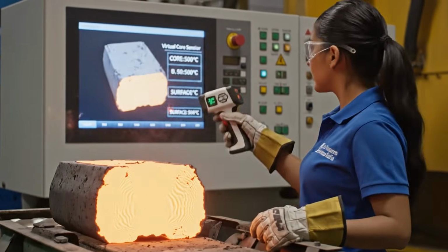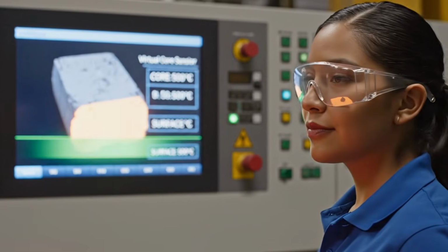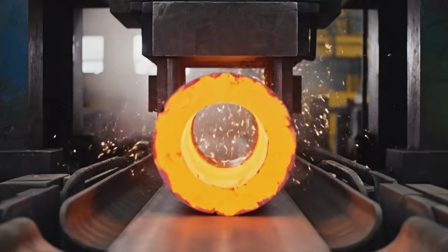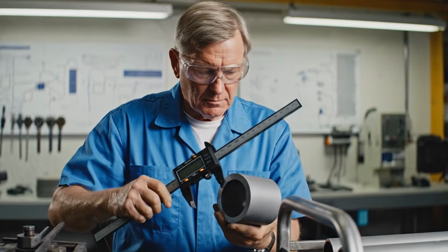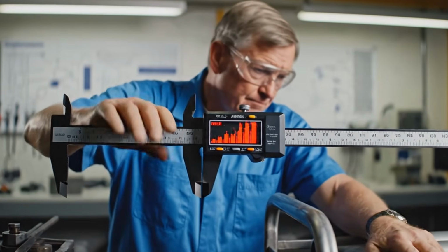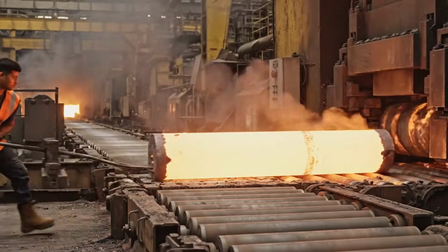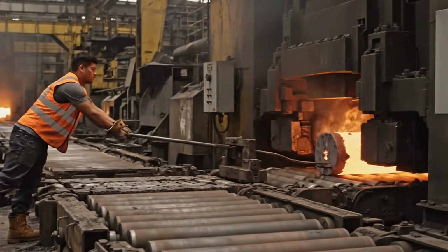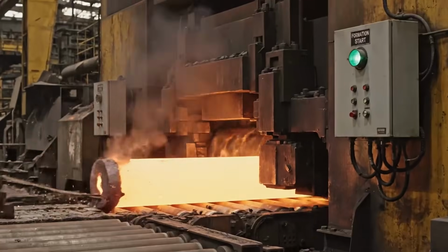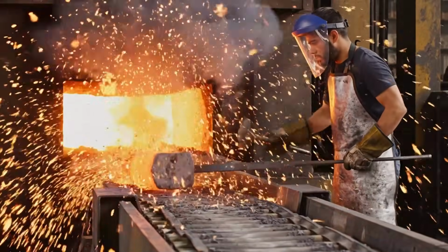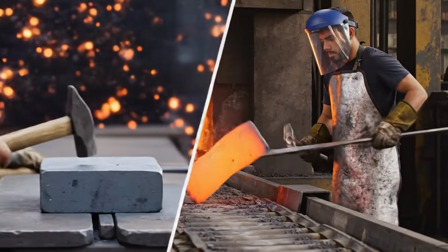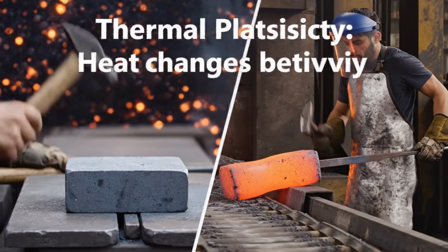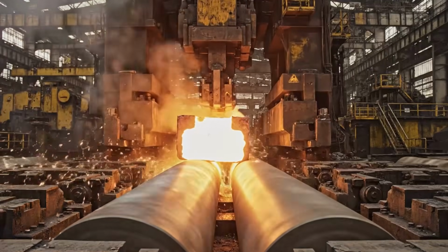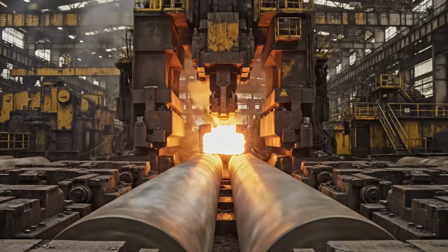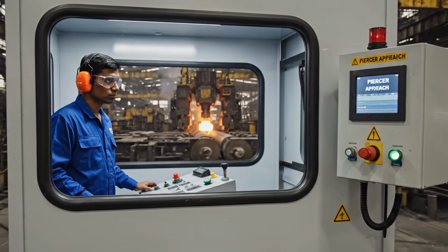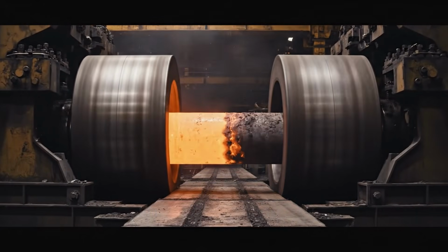The billet enters a rotary kiln or a walking beam furnace, where the temperature rises progressively until it reaches, depending on the steel and the line, an approximate range of 1,200 to 1,300 degrees Celsius. This heating does not aim only to soften the material. It seeks thermal homogeneity. The core and the periphery of the cylinder must be as close as possible to a uniform temperature so that the subsequent deformation is stable. If the exterior is too hot and the interior is still too rigid, the piercing loses precision, the metal flow becomes irregular, and the tube wall thickness begins to deviate from the first minute.